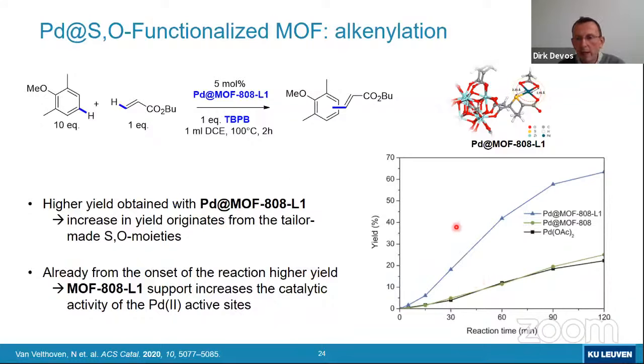And that's why this is the best catalyst in this reaction, actually. As an oxidant, we actually used tertiary-butyl peroxybenzoate, which is kind of a special oxidant, but this is an oxidant that really works really well in this reaction. Actually, this was also partially motivated by the fact that we did it in an EU project together with Janssen, with Johnson & Johnson, and they really did not want to work with oxygen.